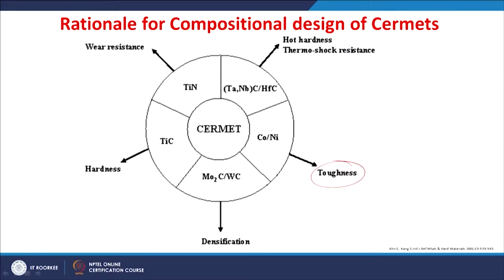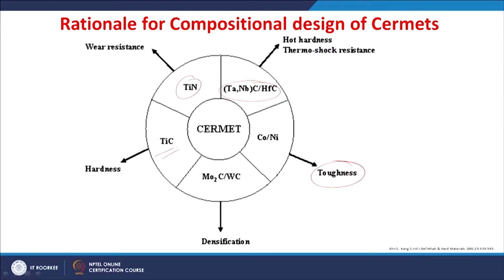So, apart from this binder phase which gives us the toughness, certain carbides or nitrides are also added to improve the performance for the cutting tool applications. For example, tantalum carbide, niobium carbide or hafnium carbide are generally used to improve the hot hardness or the thermal shock resistance. So, when these cermets are added with a combination of these carbides, they improve the intermittent cutting performance. The titanium nitride is generally used to improve the wear resistance, whereas the titanium carbide is used for improving the hardness. The densification will be improved if you add tungsten carbide or molybdenum carbide. Tungsten carbide is also known to improve the toughness of this material.